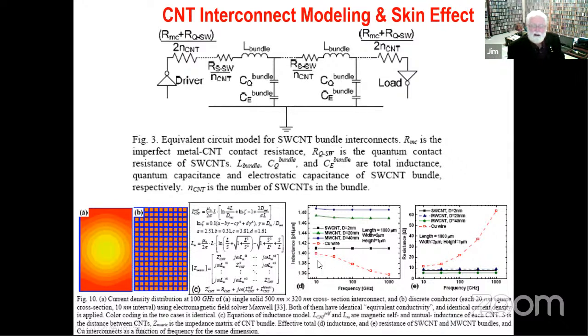For the inductance of a connector, for a copper wire it actually goes down with increasing frequency. But the inductance is not such a problem anyway. So this is the resistance; the inductance of the copper wire remains essentially the same. But the resistance, due to skin effect, takes off and skyrockets with frequency. And so resistance is the problem with signal interconnects.